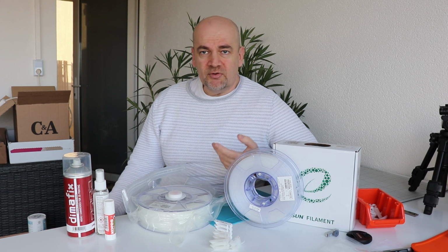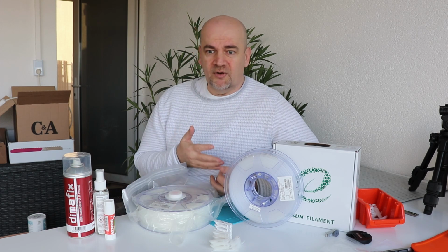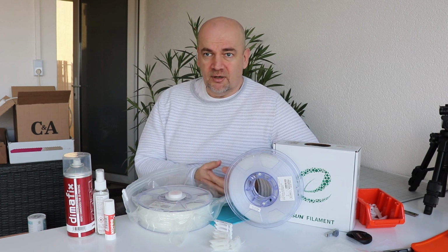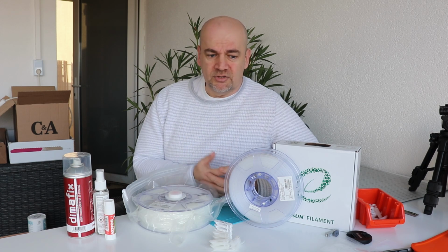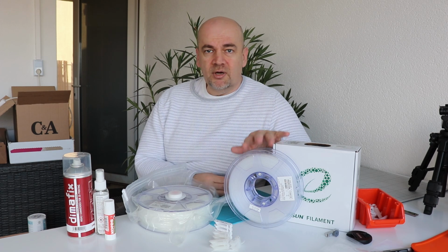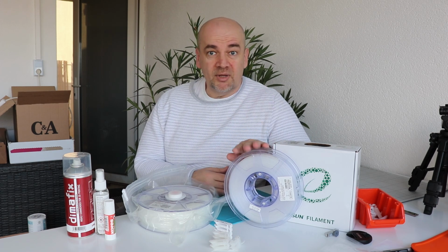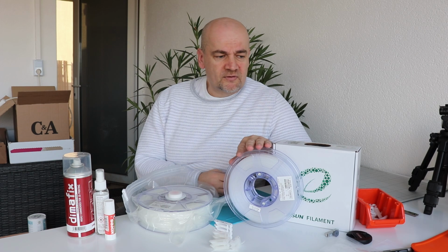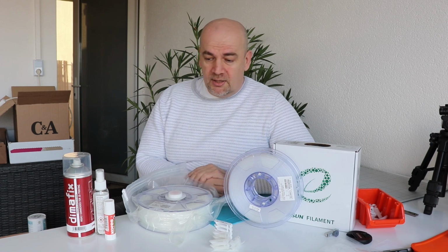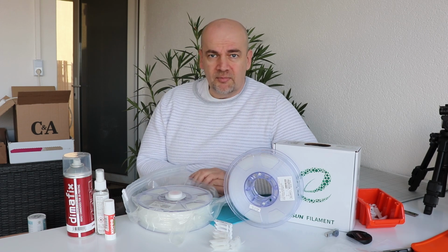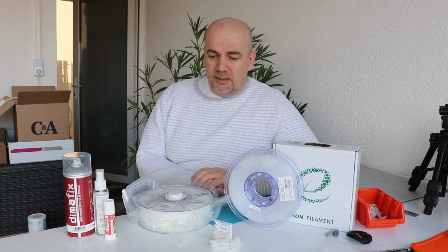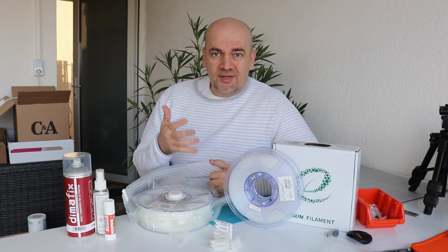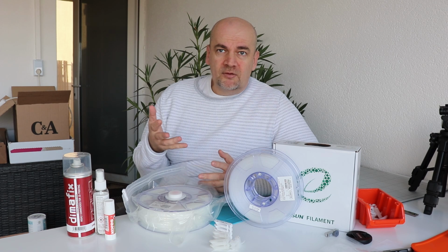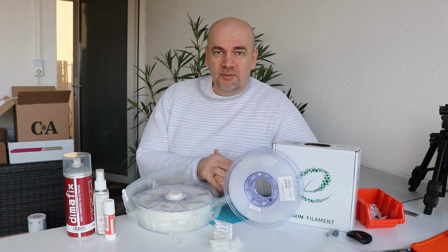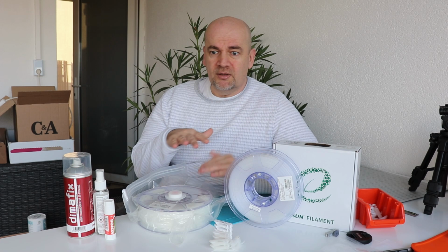For example, I was very impressed with the impact strength of the ABS Plus material, but was disappointed about weak layer adhesion. Similar with the polycarbonate, it has a better temperature resistance. And about the nylon, it's a pity that I have that very big problem with the warping, because I was really impressed with that layer adhesion. Well, maybe this means I can reduce a little bit the printing temperature, and this gives me a chance for better printing.